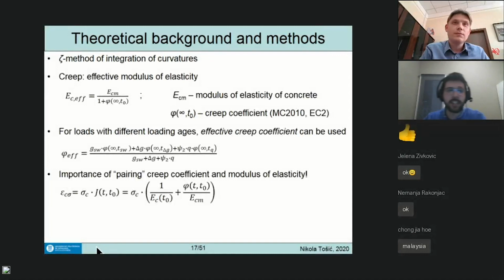So continuing later, how do we take other things into account in this Zeta method? Creep. There are more complex ways of taking it into account, like Volterra integrals and so on, but those can only be solved for a limited number of cases. The most common way is through the effective modulus of elasticity, which is the modulus of elasticity divided by 1 plus the creep coefficient.